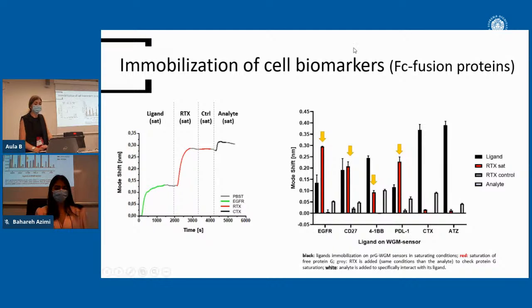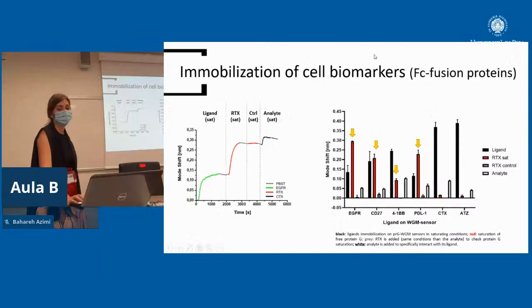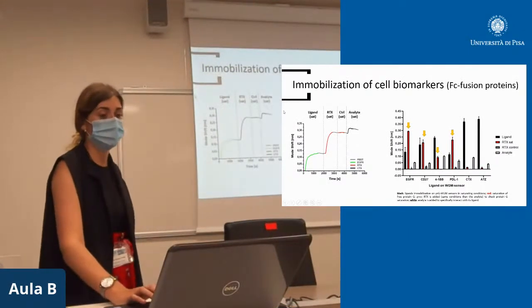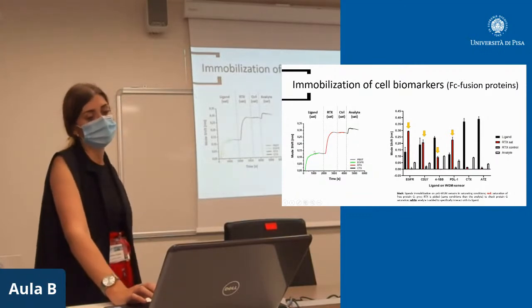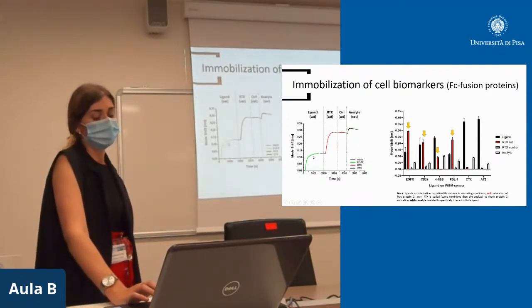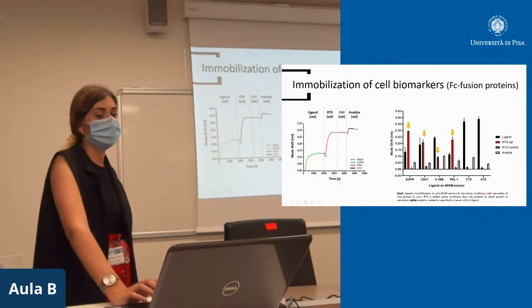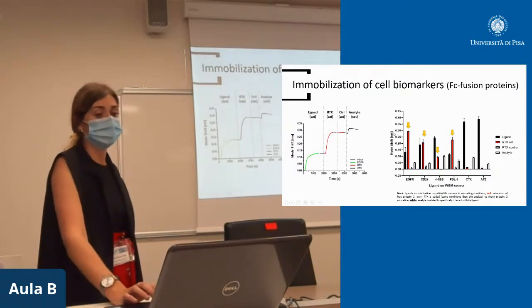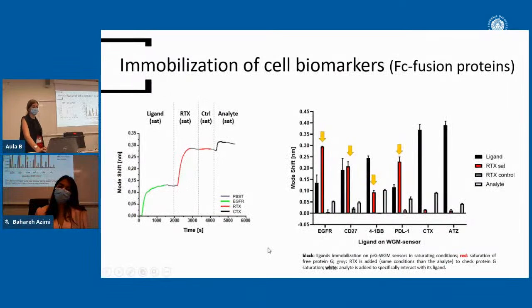And surprisingly, even though we performed the same protocols as with the IgG antibodies, with the fusion proteins we could not reach this saturation. When we add the fusion protein, in this case in green, the EGFR, we reach the plateau on the binding curve. But then when we add the control IgG, we still get a really high binding. And this happened with all the fusion proteins that we tested, as you can see here in the bars. However, for the antibodies, we didn't see this. And this is surprising, because the fusion protein has the same Fc fragment as an IgG.